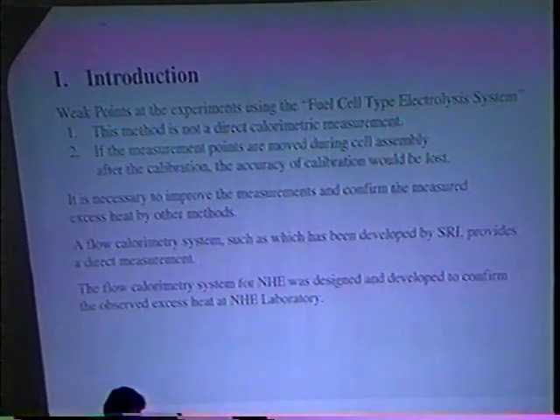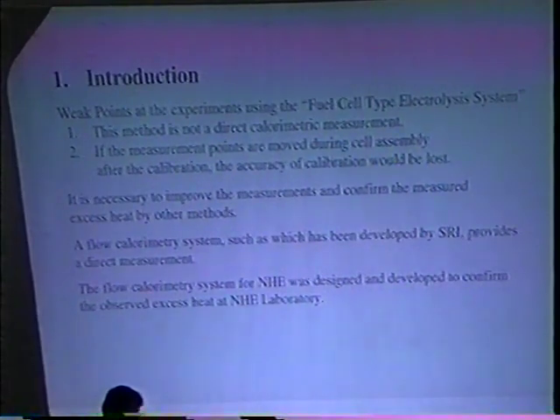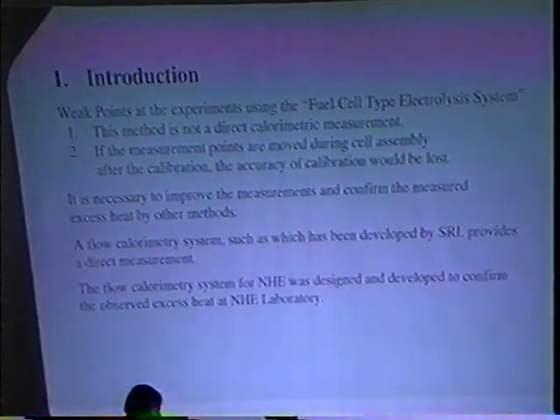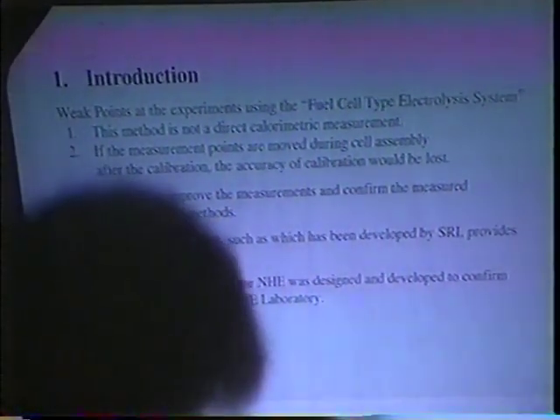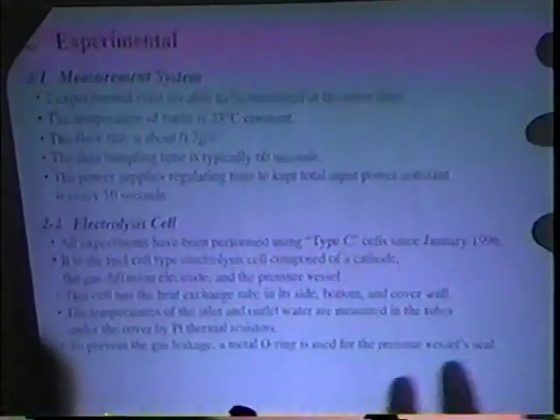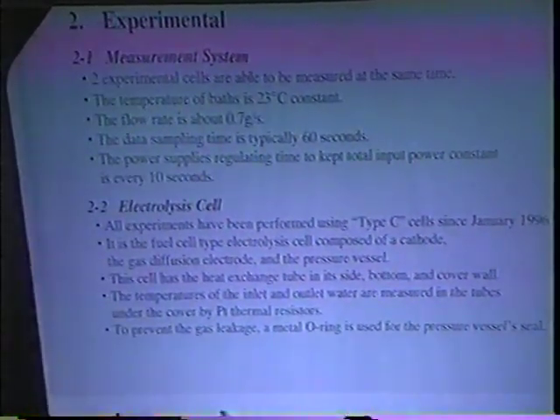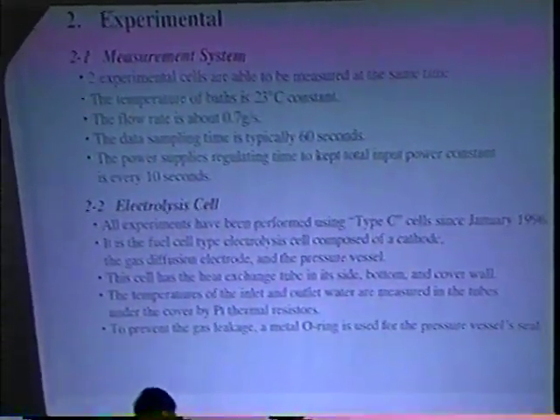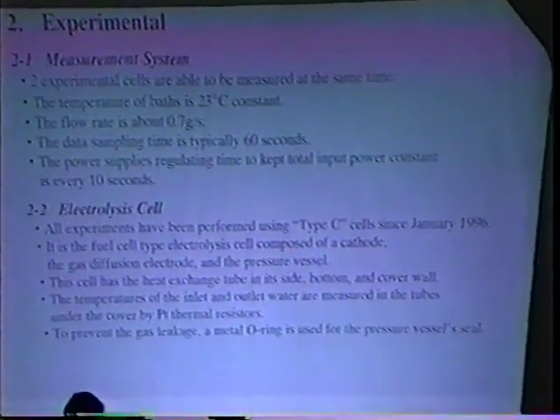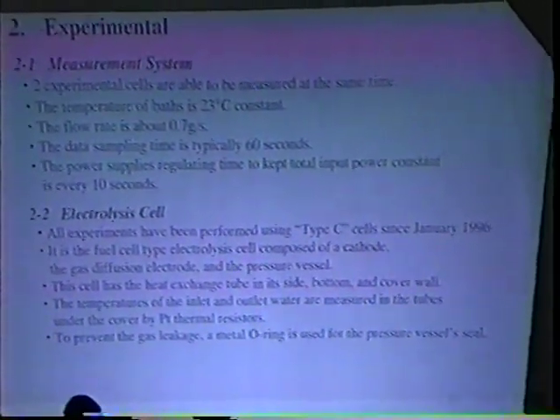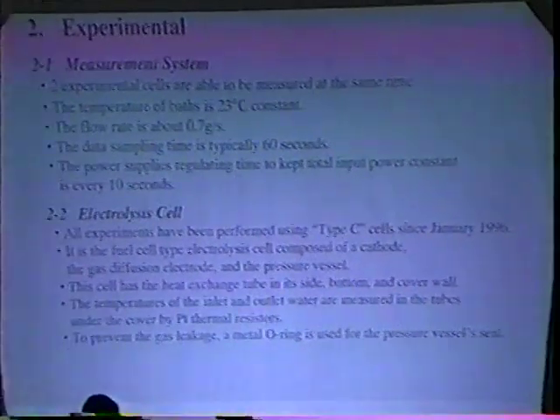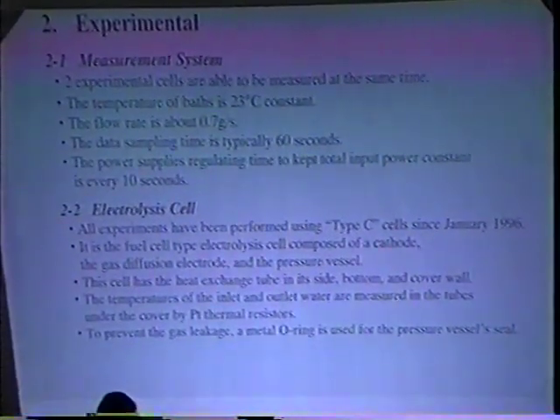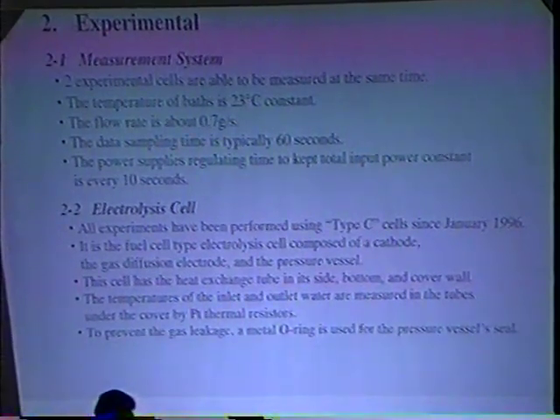So the flow calorimeter system for NHE was designed and developed to confirm the observed excess heat at the NHE laboratory. And we call it NHE-FCS. Two experimental cells can be measured at the same time in one system. The temperature of baths is kept at 23 degrees C. The flow rate is about 0.7 grams per second.